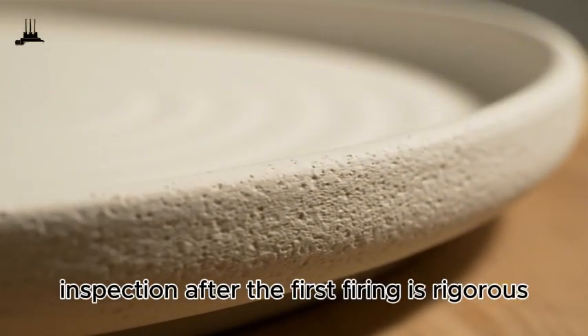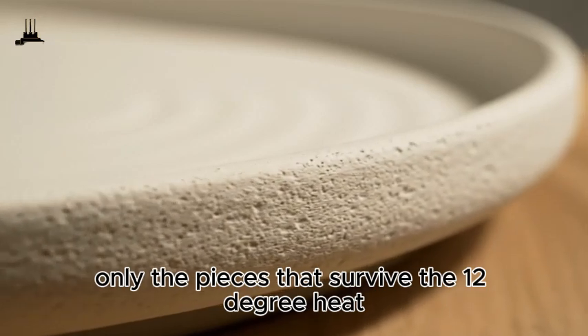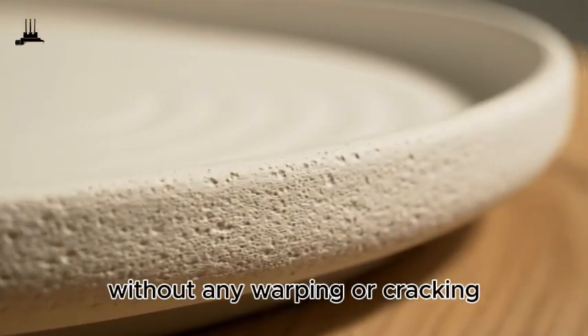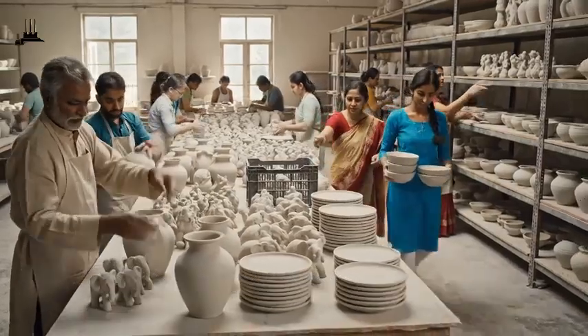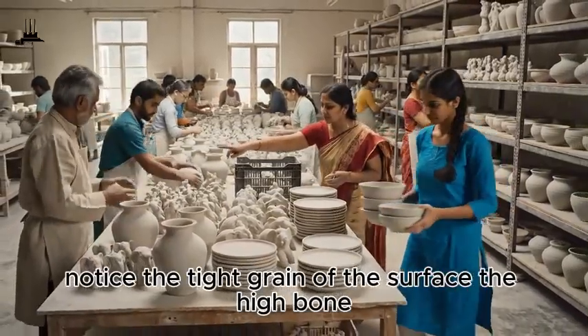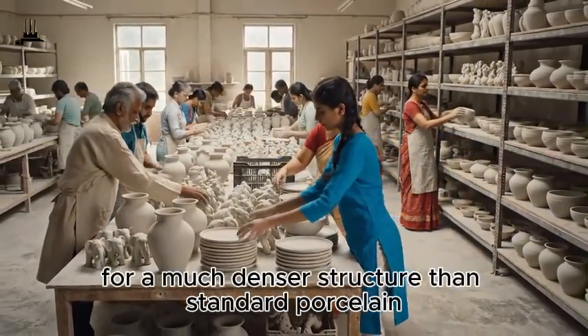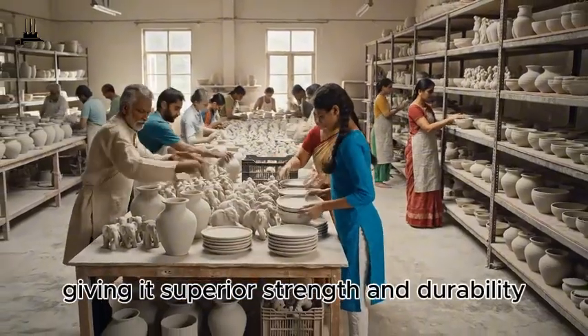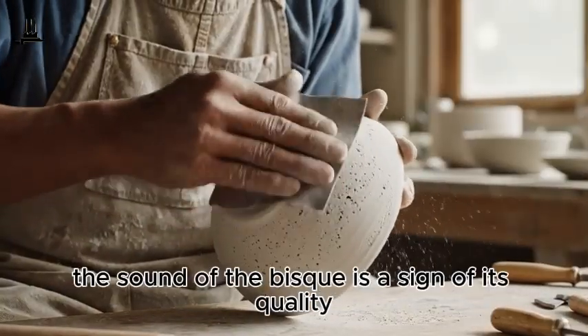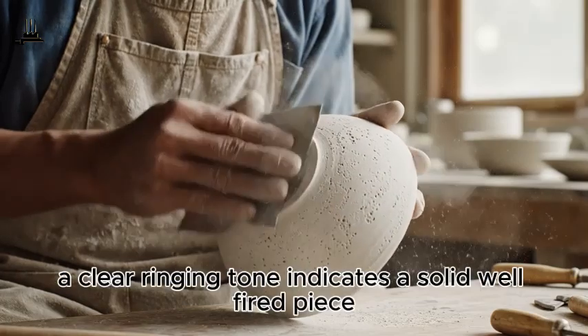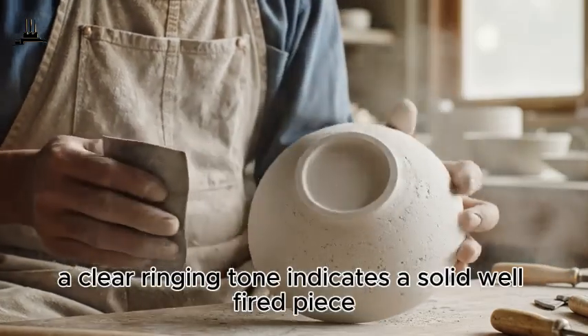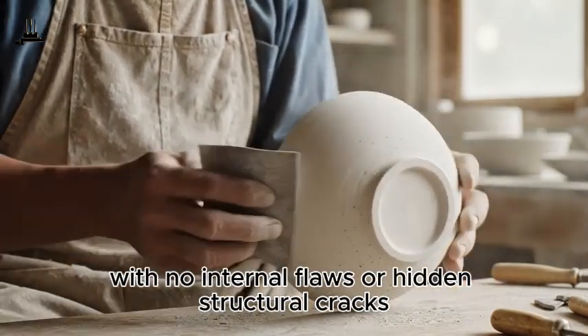Inspection after the first firing is rigorous. Only the pieces that survive the 1200-degree heat without any warping or cracking are allowed to continue forward. Notice the tight grain of the surface. The high bone ash content allows for a much denser structure than standard porcelain, giving it superior strength and durability. The sound of the bisque is a sign of its quality. A clear, ringing tone indicates a solid, well-fired piece with no internal flaws or hidden structural cracks.